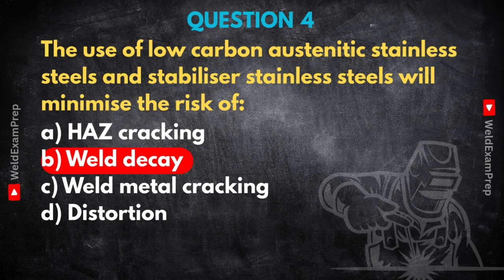Weld decay. Okay, what exactly is that? Weld decay is a specific form of intergranular corrosion. It attacks the grain boundaries. It happens when stainless steel is heated into a particular temperature range, roughly 450 to 850 degrees Celsius, like during welding and held there, or cools slowly through it. What happens is chromium carbides precipitate. They form right at the grain boundaries. This formation actually depletes the chromium from the area immediately around the grain boundary. Ah, so it steals the chromium locally. Precisely. And it's the chromium that gives stainless steel its corrosion resistance. So those depleted zones along the grain boundaries become very vulnerable to corrosive attack.